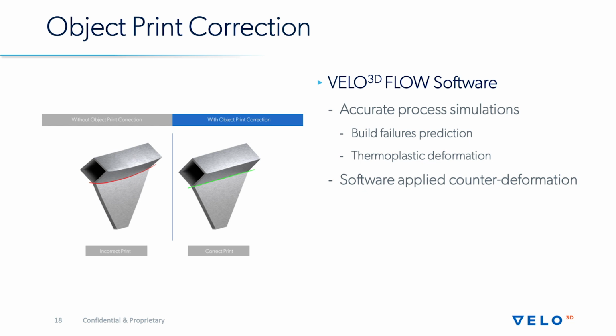The second thing you're looking for is whether or not locally you're exceeding the yield strength of any component of the part, particularly on supports, to indicate to you whether or not you're likely to have support failures in the middle of the build, which will then cause your object to move and potentially cause the part to be scrapped. The final thing is because even in the case where you don't have build failure or any supports breaking, you still have this large-scale deformation that's present in many parts. And the software is now able to actually pre-deform the geometry such that when you print it, it deforms back into the correct net shape.